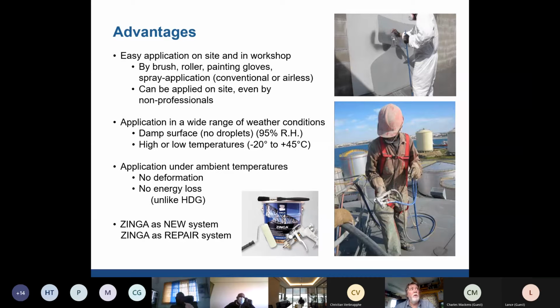You can apply it in a very wide range of weather temperatures. If it's -20 up to 45 degrees, you can apply Zinga. If it's 95% humidity, you can apply Zinga. You cannot apply paints anywhere in the world above 70% relative humidity. If you do that, it'll fail. You'll have blushing and blooming with things like epoxies, because they absorb moisture from the atmosphere, and you get blooming, which is big white blotches all over the paint, and all sorts of problems like that. And it will delaminate on many coatings like PUs and so on. So with Zinga, up to 95% humidity, you have no problem at all.